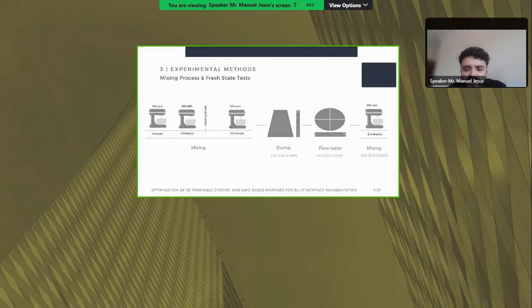At this stage, fresh state characterization was conducted, namely the slump and flow table tests according to EN standards. And finally, the mortar received another quick remix to maintain its consistency before being loaded into the extruder cone and printed.